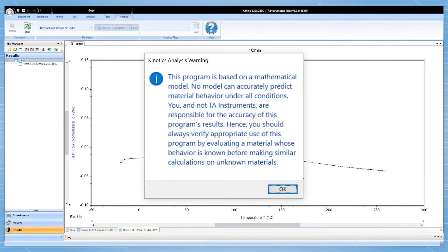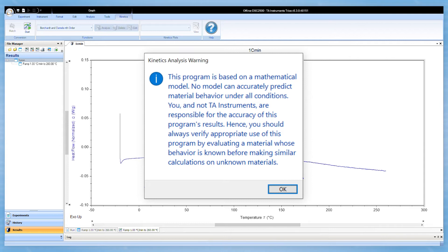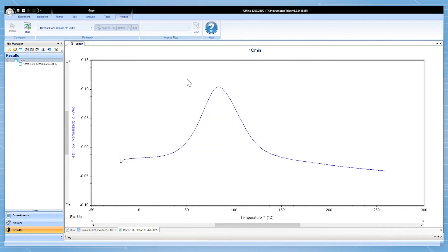A warning will pop up reminding you that it's important to remember that kinetics obtained in DSC experiments may not be fully representative of other environments such as a manufacturing process. It's important to keep this in mind as kinetics data is generated in TRIOS. DSC can give powerful insight into the kinetics of a process but can be limited to being a comparative tool rather than replicating other conditions.